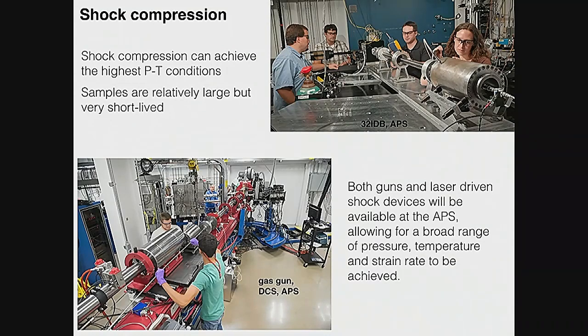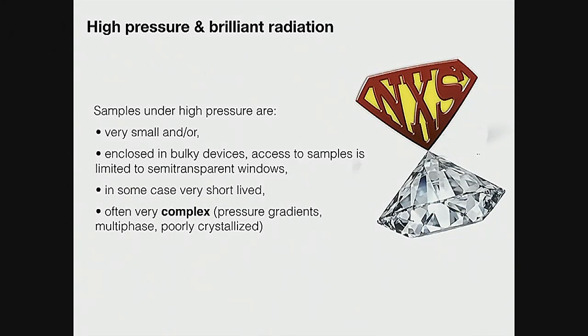So usually the sample will also heat up because of the energy being applied at this extremely fast rate. You have strain rates that are extremely high, and you have a shock wave going through. So given these conditions that I summarized, it's quite obvious why the high pressure community loves these laboratories.